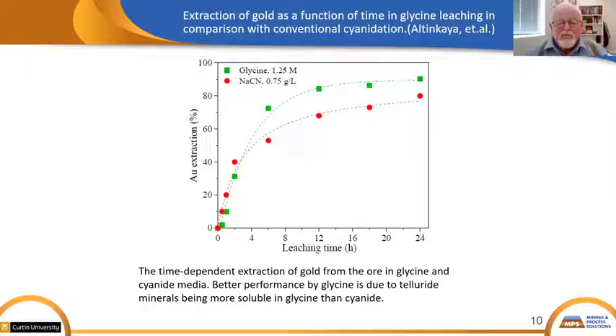Both suspensions were strongly agitated, and it shows that the heated, high pH glycine, this is 60 degrees C, the pH of 12, with a superior recovery to straight cyanide. There's what appears to be a much better finish to the leach curve, and the authors of the paper ascribe this to the fact that the tellurides must dissolve much easier in glycine than in cyanide, and accounts for the better finish.